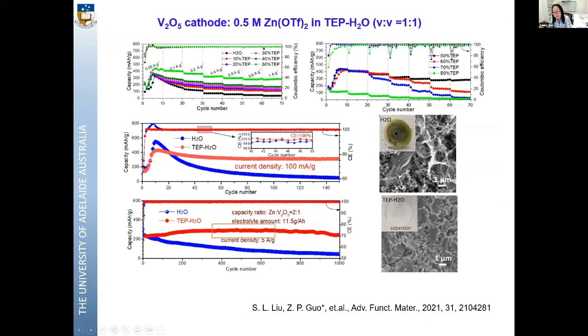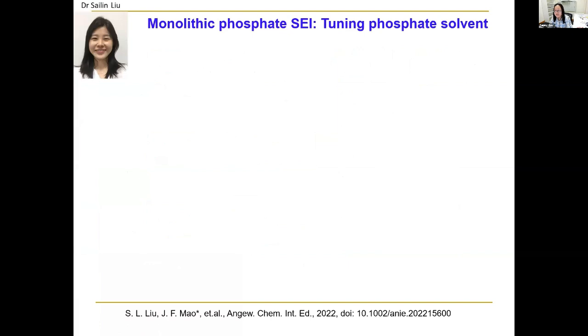So the full cell in this hybrid electrolyte, under lean electrolyte condition, low NP ratio 2, can be charge-discharged for 1,000 cycles with capacity retention of nearly 200 milliampere hour per gram. It's even better than the previous in situ organic SEI data. So apparently, we compared three different kinds of SEI and their influence on the electrochemical performance of zinc-ion batteries. Besides that, we found that in the composite SEI, with organic and inorganic components, the distribution of each component may not be that uniform at the nanometer scale. So if we can develop an SEI with a monolithic phosphate structure, then it could be even better.